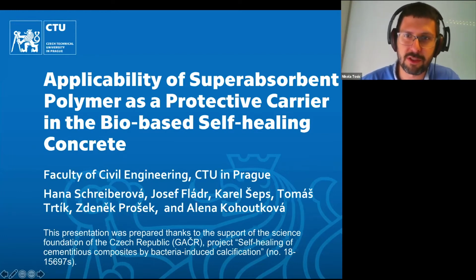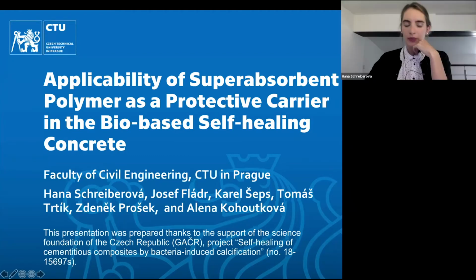Is there a reason why you are using a cement type 1, 42.5? Did you compare with limestone cement type 2? The cement type 1 we applied just because it's the most common one in the Czech Republic. So we wanted to do a replicable study. We tested with the cement type 2, and the self-healing itself, the autogenous self-healing, was decreased. However, the mechanical properties dropped significantly, and it was very hard to work with the samples, as they tend to lose their strength completely, so the cracks wouldn't form and we could not see the self-healing. We just destroyed the samples. So then we used cement type 1 further.